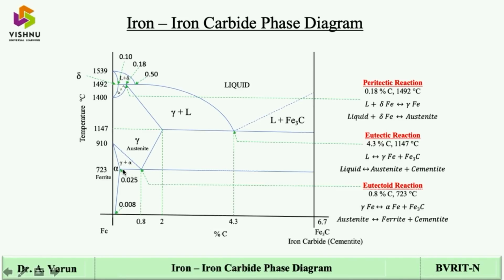Then the third one, eutectoid reaction at 0.8% of carbon, 723 degrees centigrade, gamma iron austenite will transform into ferrite plus cementite, which mixture is called a pearlite mixture. Now here another important thing you need to remember is austenite, which is formed in the eutectic mixture, will not be stable below 723 degrees centigrade. They further transform into either of the forms of pearlite. So austenite below 723 degrees centigrade is not stable, which will again transform, that is this transformation line.